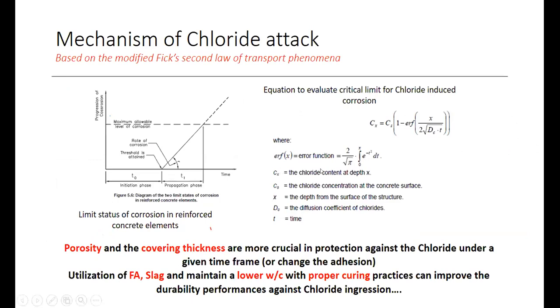You can see the main things here. Cx means the chloride content at depth x, because to initiate the corrosion of steel, it has to reach the critical limit of chloride concentration. Utilizing this equation, we can identify how much time it will take to reach that level. The key governing factors are the concentration at the concrete surface, the depth from the surface of the structure, the diffusion coefficient of chlorides, and time, which determine how long it takes to reach the critical limit that can lead to corrosion of steel.